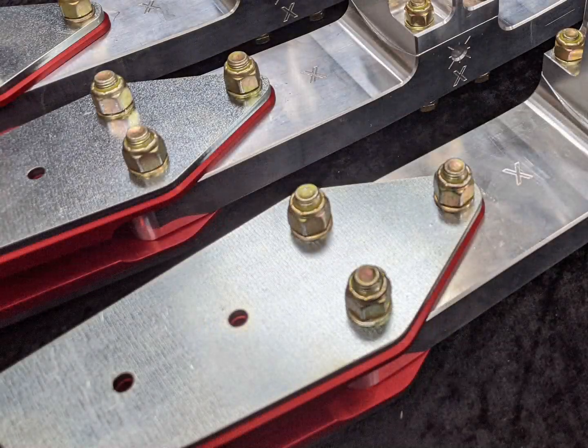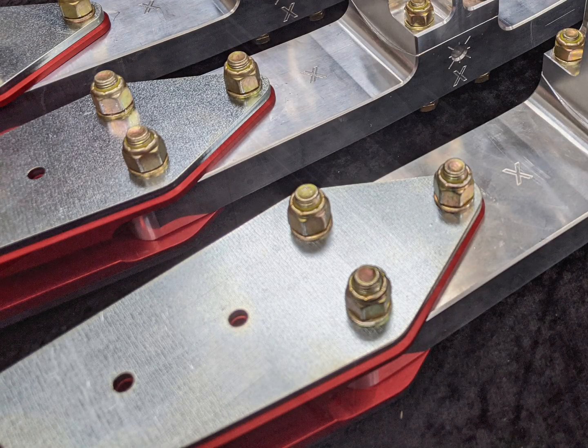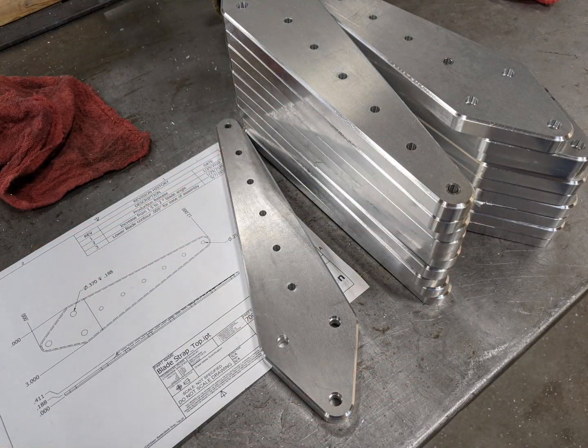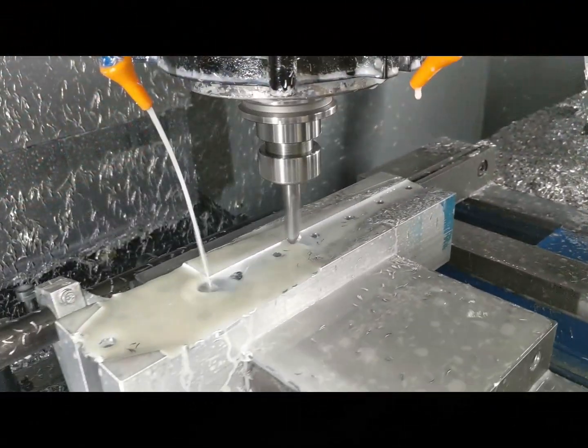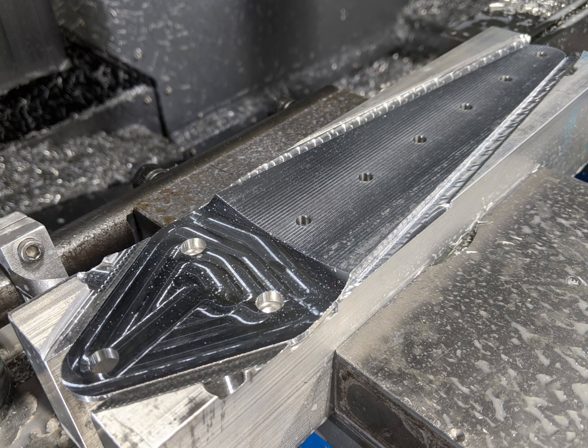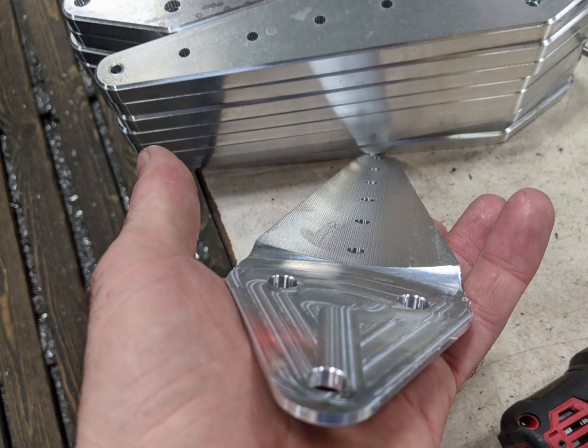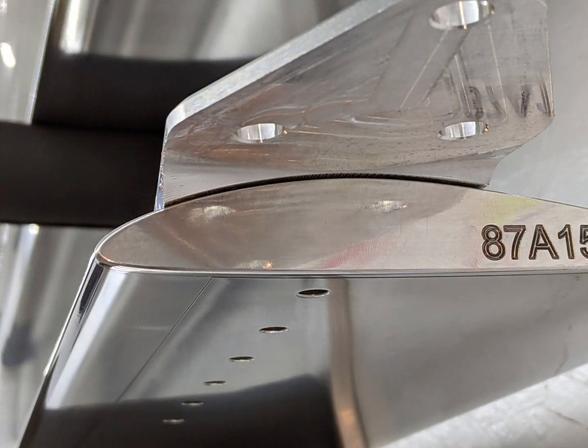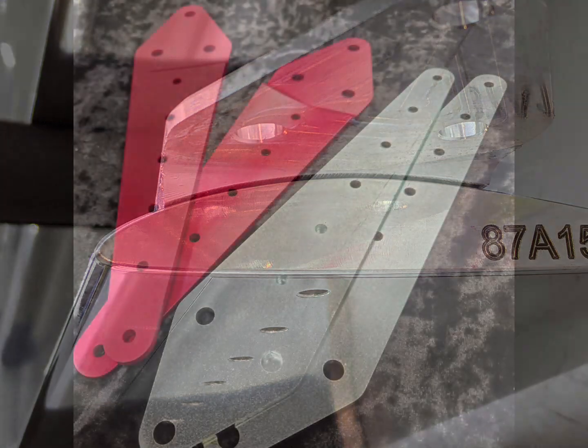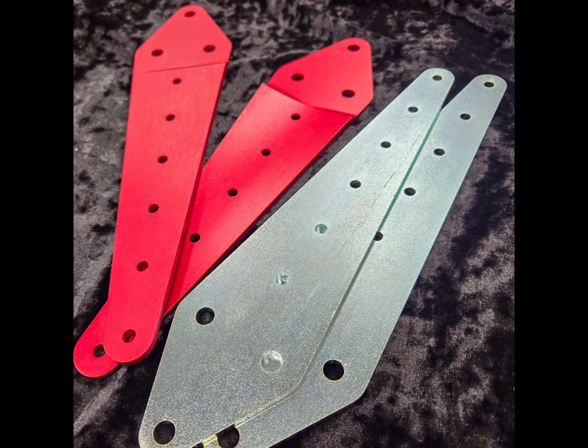Of course, it's the straps that join the hub bar to the blades themselves. These are in 2 pieces. We have the inner straps, or spacers. They're machined from aluminum that match the 87A15 profile of the blades. There's a separate one for the top and the bottom. The profile hugs the airfoil exactly and provides a perfect match against the blade with no pinch areas or gaps. Those are then topped by some 3/16 80,000 psi steel plate straps for fatigue resistance. The inner aluminum straps are anodized, and the outer steel straps are zinc plated to protect against corrosion.